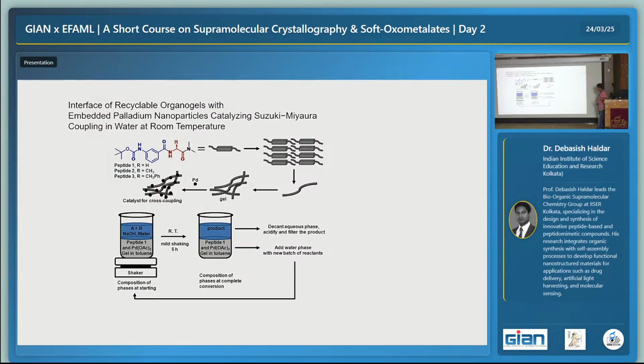And again, the concept is very simple. We just put a layer of the gel at the bottom of a glass container, and then on top we add an aqueous solution of reagents A plus B in NaOH solution in water. Now if the gel is there and on top is the aqueous layer, we cannot use a magnetic stirrer. So we have to shake the whole reaction system.